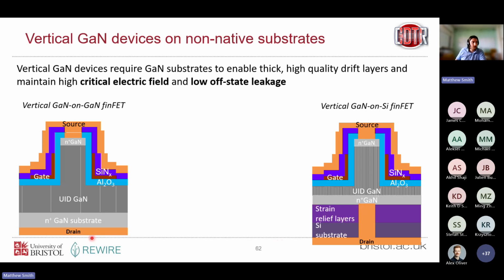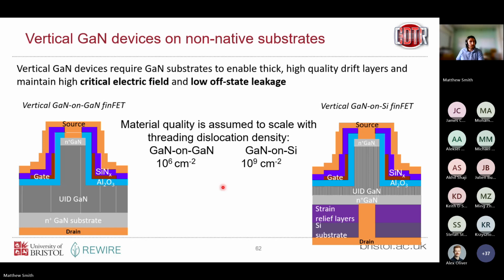So we can't just deposit our drain contact on the backside. We have to etch through our silicon substrate, etch through our strain relief layers, and then stop on our embedded N+ GaN layer in order to achieve something like a vertical device in this GaN on silicon.